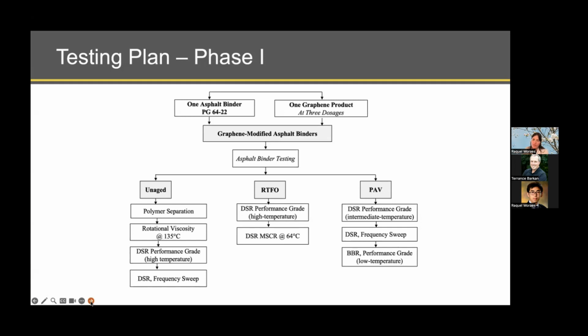But before moving to that, we need to acquire the basic knowledge of how these products work, how we can work with them in the lab, and so forth. So you can see here we have 1 asphalt binder, and for each graphene product, we evaluate 3 different dosages. We evaluate the material when we call it unaged, meaning that we have your additive, we blend it with the asphalt binder, and we evaluate properties of that material without submitting the final blend to any type of oxidative agent.